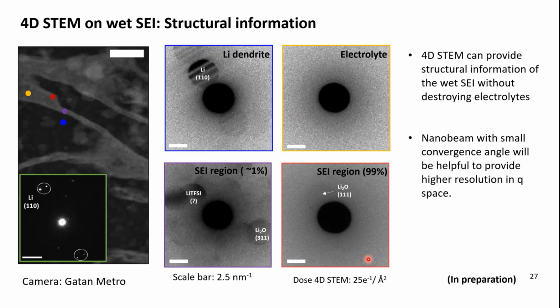So we first performed 4D STEM on wet SEI, and you can see that with really low dose rate, you can clearly see the diffraction pattern of lithium dendrites and amorphous structures of the vitrified electrolyte. Our assumption on the wet SEI was that there could be some lithium TFSI salt diffraction patterns, but unlike our expectations, they are not there. The majority of the SEI was amorphous structures, which means that there are still some amorphous features in the wet SEI.